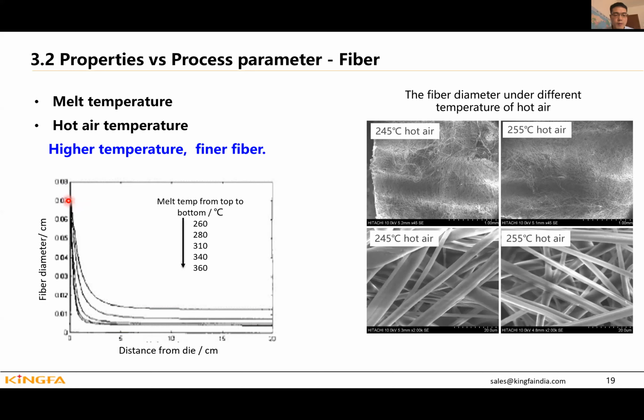When the PP melt comes from the hole, the dimension is about 70 micron. But after the hot air extension, it decreases to 5 or 10 micron. So if the temperature goes from 260 to 360, the final fiber diameter can decrease to about 5 micron. So if we want to get a finer fiber, we need to increase the melt temperature. So this is the melt temperature influence.